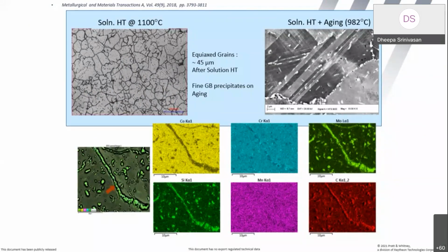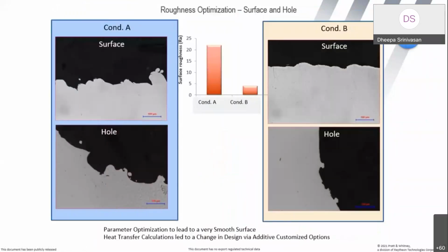In this particular case, we found it to be a much slower creeper because all the grain boundaries are pinned by these precipitates, black and white. I won't go into the details of it except to say that the fine grain boundary precipitates come on aging. And then the next, challenge number 5, now we are coming down to it.